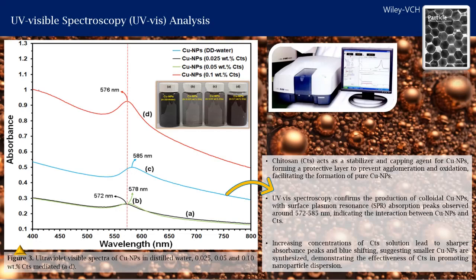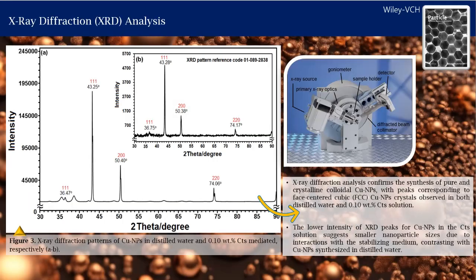UV-vis spectroscopy analysis reveals chitosan stabilizes and caps copper nanoparticles, aiding in pure copper nanoparticles formation. Colloidal copper nanoparticles are confirmed, showing surface plasmon resonance absorption peaks at 572 to 585 nanometers. Higher chitosan concentrations lead to sharper peaks and blue shifting, indicating smaller copper nanoparticles and enhanced dispersion.